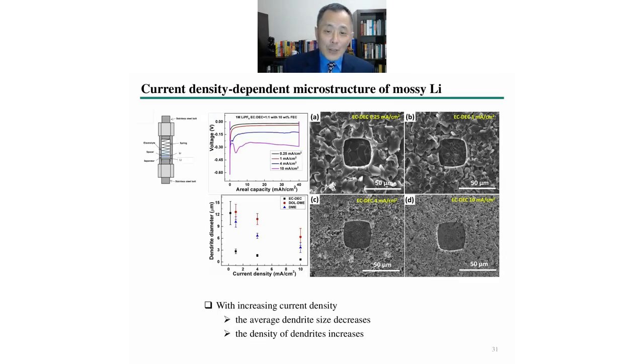The next question, of course, is to study the lithium produced during the electrochemical cycling of the battery, where lithium foil is used as the electrode. As the SEM images show, the electroplated lithium can have very different microstructure than the lithium foil produced by rolling, for example.